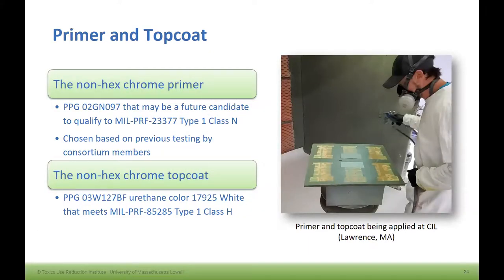Then the primer and top coat. So we used a PPG product that was actually not even qualified yet for the MIL standards, but the members of the consortium had done a lot of internal testing on that primer, and they felt that it was the best one on the market, even though it wasn't qualified, that it would be soon. So we used that. And for the non-hex chrome top coat, we used another PPG product that was qualified. And we applied those, the primer and the top coat, at CIL in Lawrence.